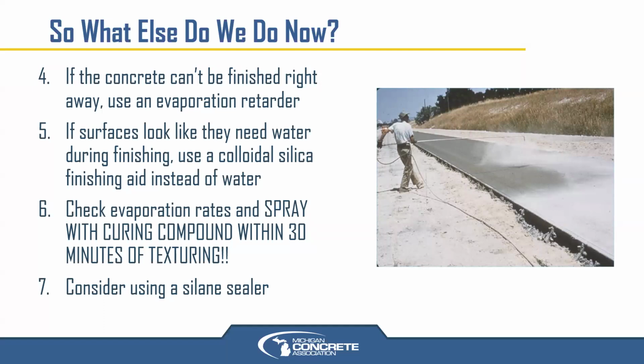Number 6 there says, be checking your evaporation rates. And then based on evaporation rates, you may need to get on even before 30 minutes of texturing. But there are some simple tools out there. It's portable handheld weather stations, $300 to $350 for a little one. We have one here in our office, for example, that can tell you what the wind speed is, can tell you what the relative humidity is, can tell you what the temperature is. And it's either handheld or there are ones you can put on a little tripod, a little mini weather station, and put out there as well.